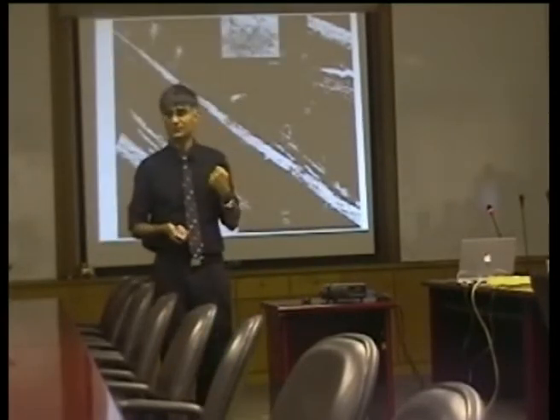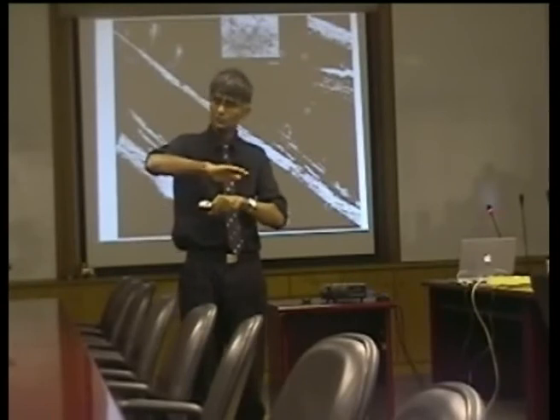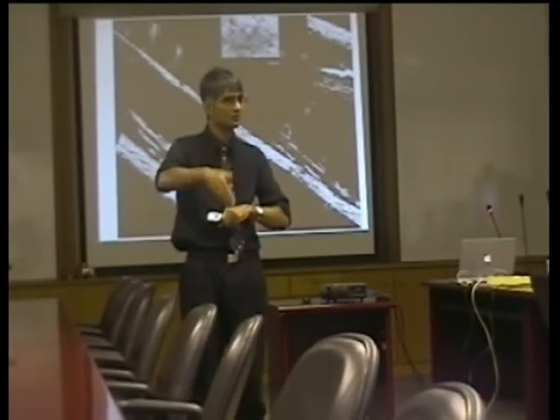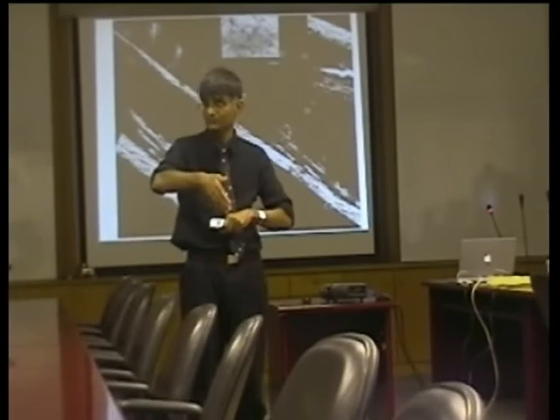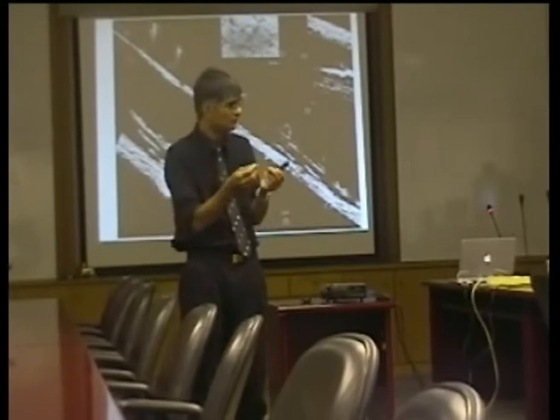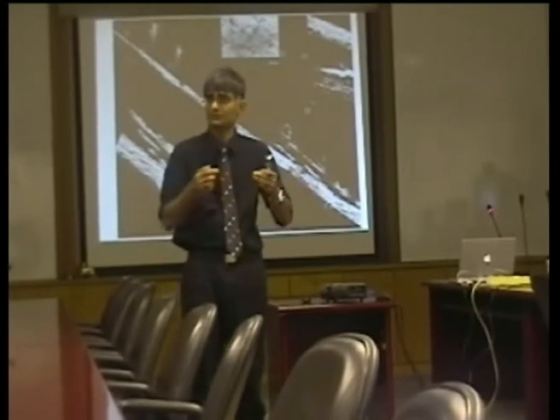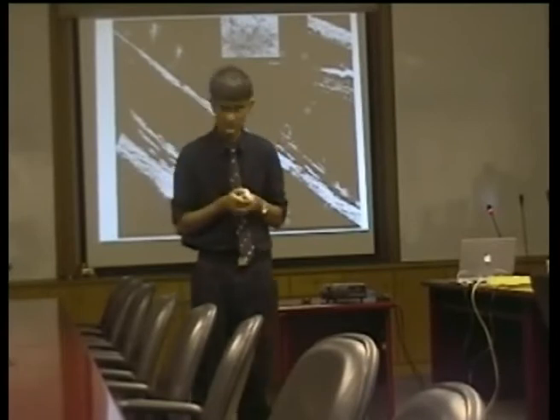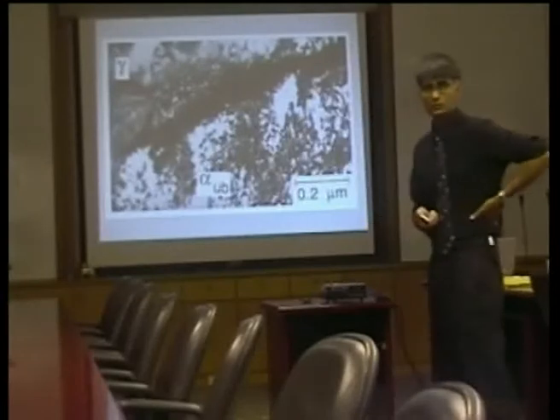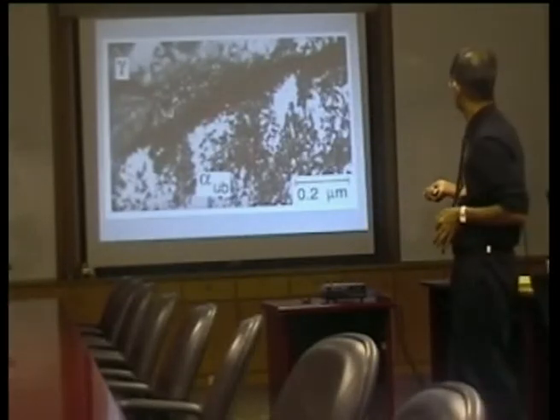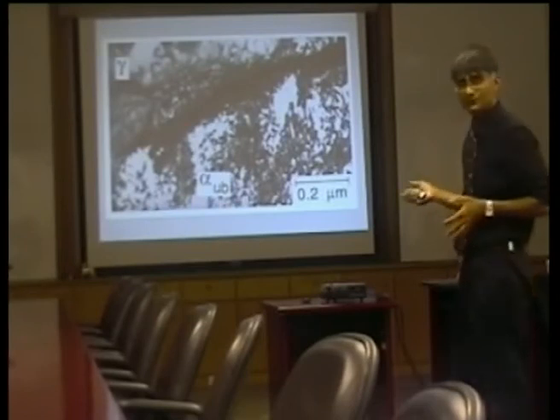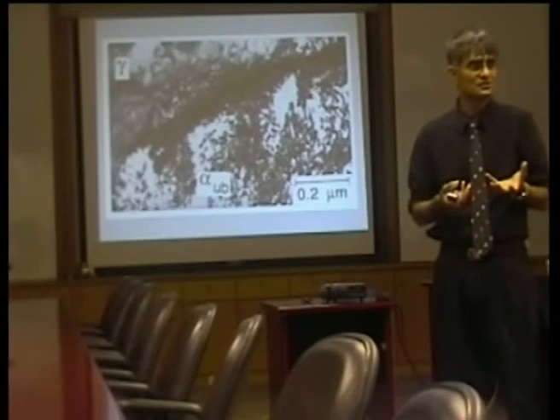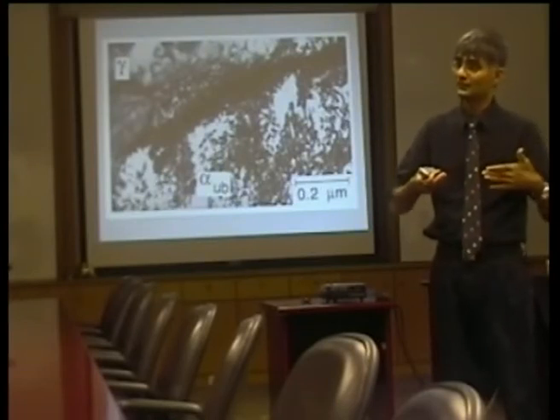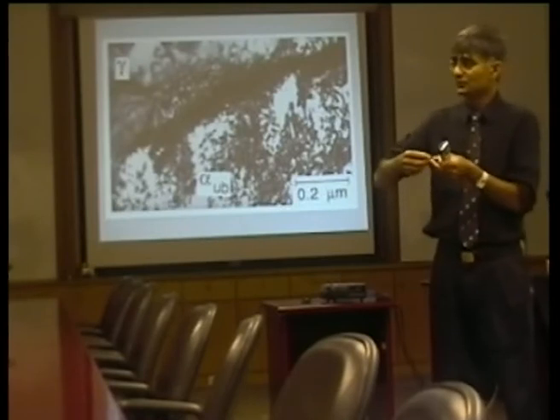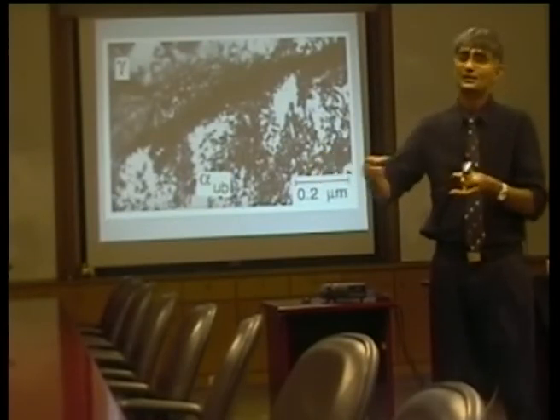Now, many, many years ago, we suggested that the reason why this is happening is that the transformation causes plasticity in the austenite, and that stops the interface by mechanical stabilization. I mean, it stops growing, because you've introduced so many defects in the austenite that the interface between the bainite and austenite cannot move. And if you look closely at the interface between bainite and austenite, you can see a huge array of tangled dislocations. So basically they are stopping the interface from moving. So for the transformation to progress, you have to form a new plate. And that's what's stopping it.